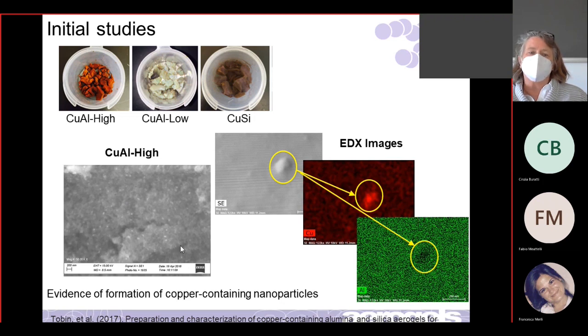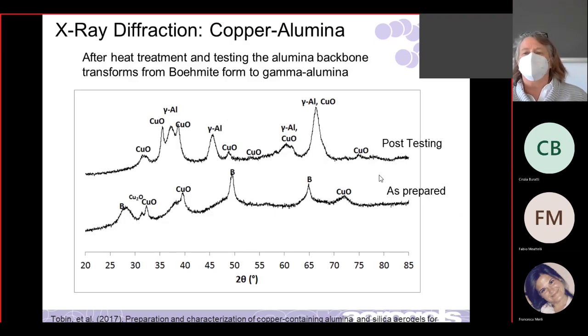And so then we did X-ray diffraction. And so X-ray diffraction gives you information about the crystalline form of things. And so basically you get a pattern that on this axis is intensity of a signal. And this is the angle that you have a sample and your X-rays are moving around different angles. And so where you get peaks is related to different crystalline structures. 5 or 100 structures could have a peak here, but it's the pattern of peaks.